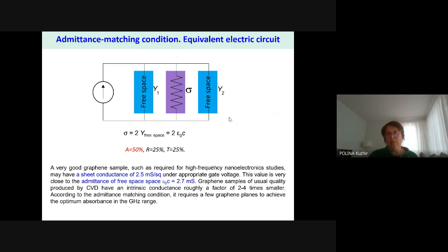We found that the sheet conductance of high quality graphene, like exfoliated graphene, is almost equal to the admittance of free space, 2.5 versus 2.7. So it looks like you need just 2 graphene layers in parallel in order to achieve this admittance matching condition. So you could absorb 50% of electromagnetic radiation when you have just 2 graphene layers of proper quality.